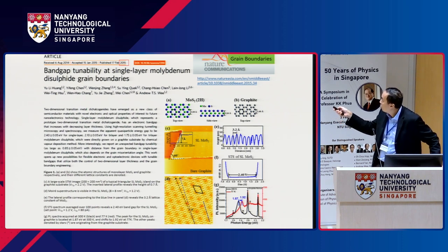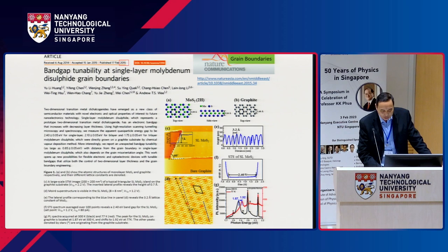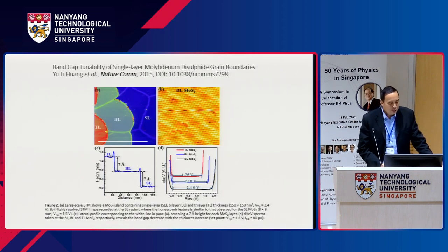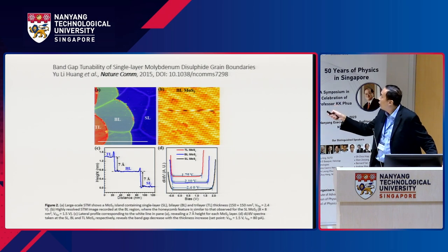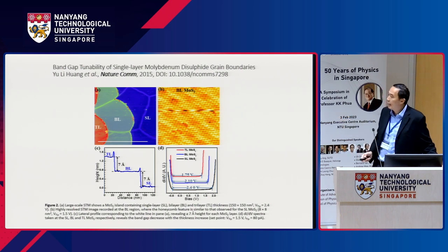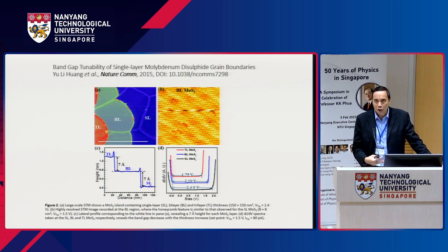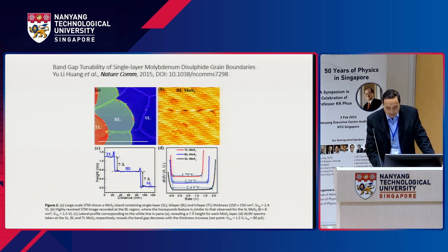You see the moiré pattern because it's on top of graphite, which has a different lattice constant. And you can see the band gap here as well. This is the electronic band gap. So we started looking at a different source of 2D materials. It turns out these materials are very interesting because whether it's single layer, bilayer, or trilayer, you can see here, they have different band gaps. The single layer has the largest band gap, the bilayer has a smaller band gap, and the trilayer has an even smaller band gap. So you have another handle to control the electronic structure of these materials. If you imagine making a device from these materials, if you could control the number of layers, you could also control the properties of the devices that you have.